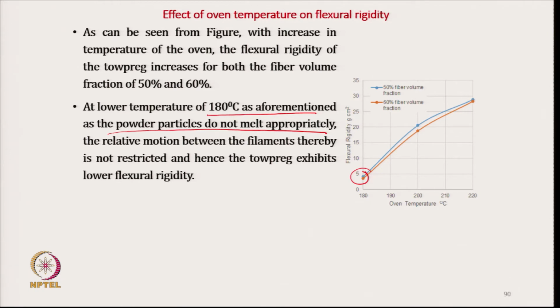So, what happens if it does not melt, then there will be relative motion between the filaments. So, there is no proper coating. There is a fiber, and these are the particles. So, there will be relative motion between the filaments, thereby the movement is not restricted.